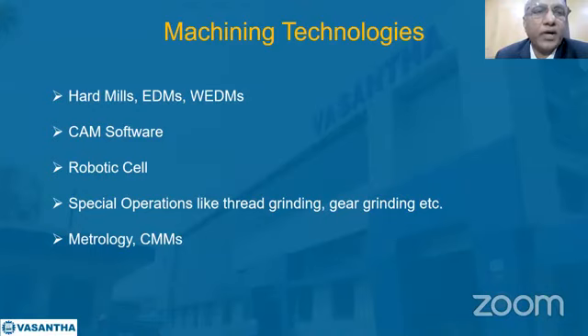So we use high precision hard mills. The concept is that you cut the steel at high feed and high speed, but with very little depth of cut. When the depth of cut is small, you have very little surface finish variation. In fact, we often use 0.05 depth of cut, and for the finish cuts, we even give 5 microns, 10 microns, and 15 microns. When you are running at such depths of cut, the surface finish variation cannot be more than the depth of cut.